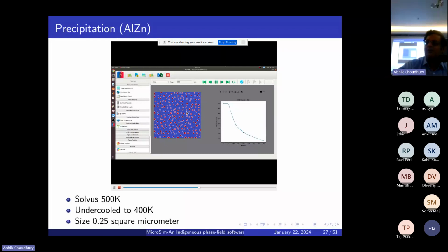Essentially, you have one solid emerging from the other solid, precipitation. Because it goes from a growth regime to a coarsening regime, you will see that after a certain stage, the larger precipitates grow at the expense of the smaller precipitates because the saturation in the matrix runs out. Okay, and you can plot several things. This happens after solidification. It is a process that would typically happen during the heat treatment that follows solidification.